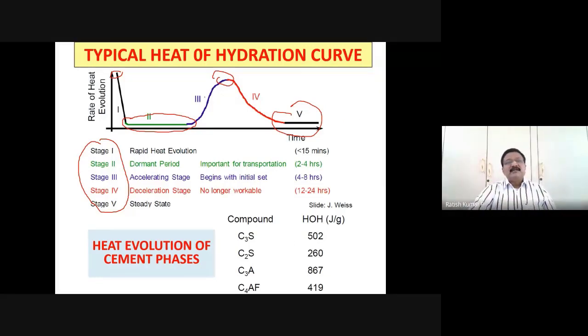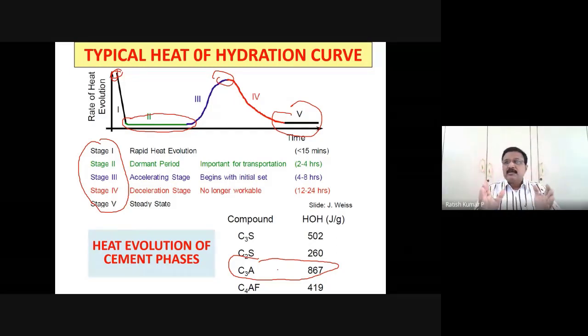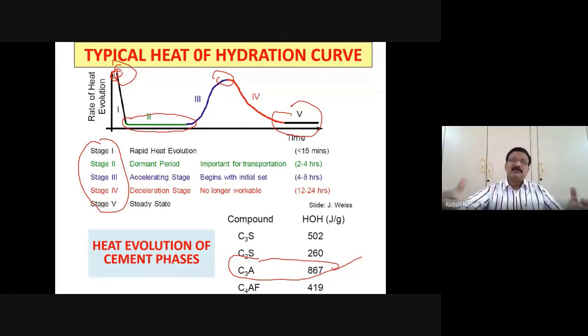You can notice here that the initial heat burst is basically because of the large amount of tricalcium aluminate which is going to form. This is a very active reaction which takes place when cement comes in combination with water. The first and foremost reaction, which develops a huge amount of heat evolution from all the cement phases, is this tricalcium aluminate. You can see it's a good 867, and that is the reason for the initial heat burst here. And then of course the next is tricalcium silicate, then tetracalcium aluminate ferrite, and then dicalcium silicate. Tetracalcium aluminate ferrite basically is responsible for the grayness in the cement. That's the reason.